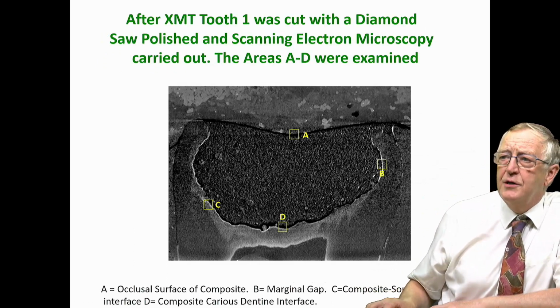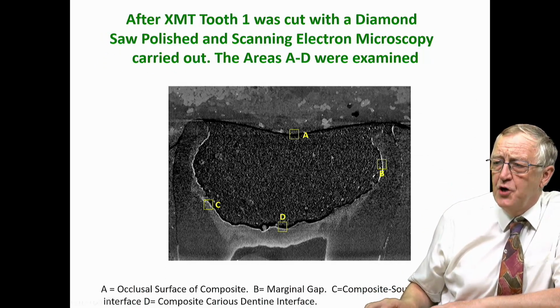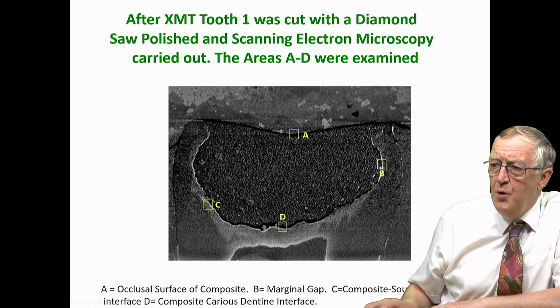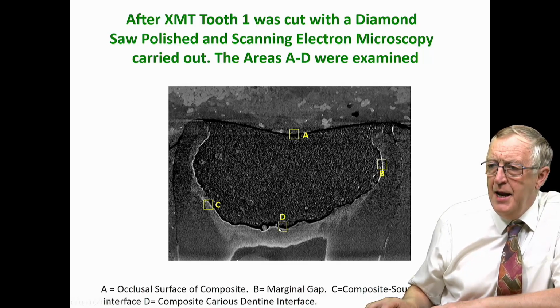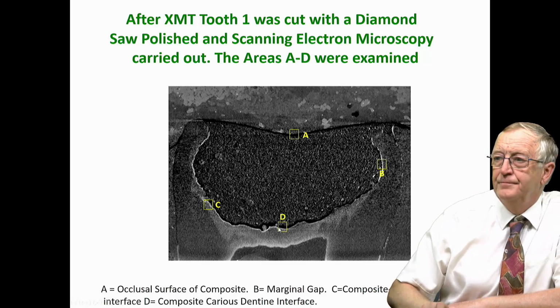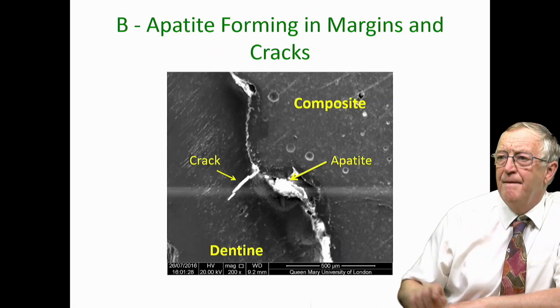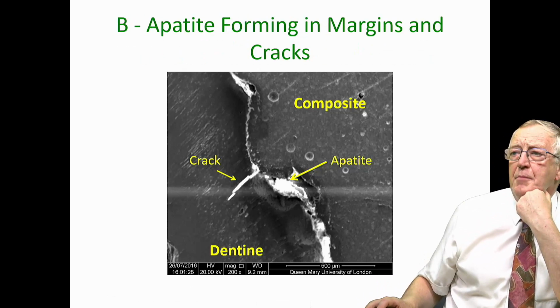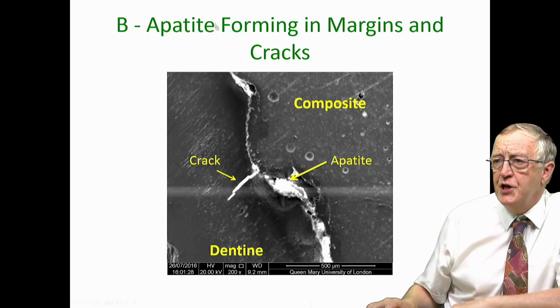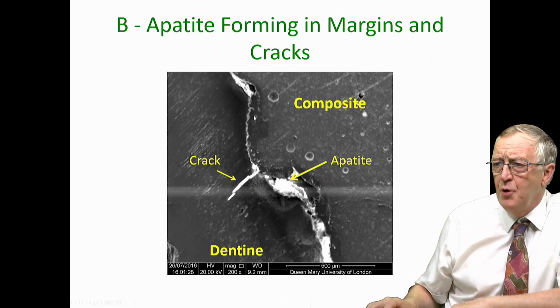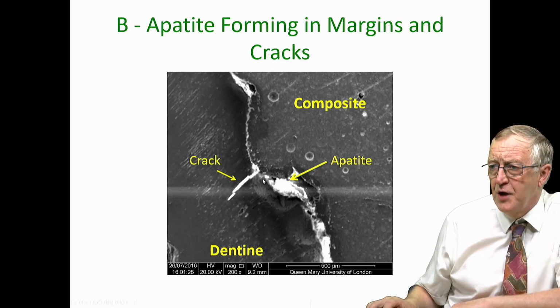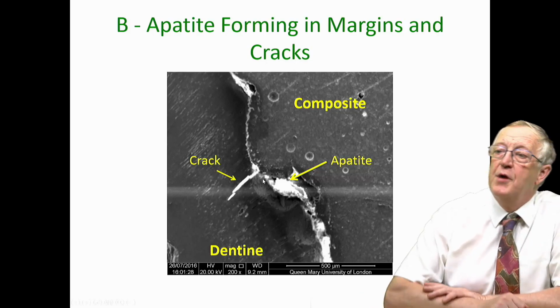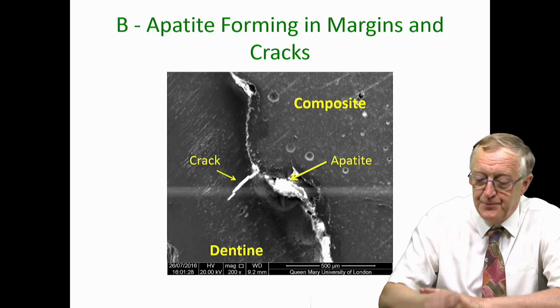We're now going to look at SEMs, look at the microstructure after we slice the tooth with a diamond saw, and we're going to show you micrographs corresponding to here, here, and here. So this is in the marginal gap, and what you can see is we've got this white deposit in the marginal gap and even in the crack that runs off the marginal gap, and this is apatite forming in the marginal gaps.